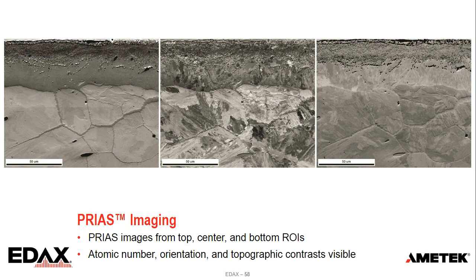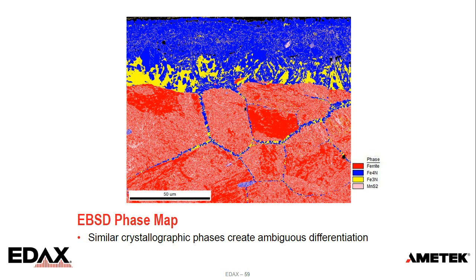If we look at the phases, we see here there's the ferritic phase in red. The blue and yellow phases are a couple of the nitride phases. And then there's a manganese sulfide phase as well. But it has some trouble differentiating these. There's some speckling within the base ferritic grains.